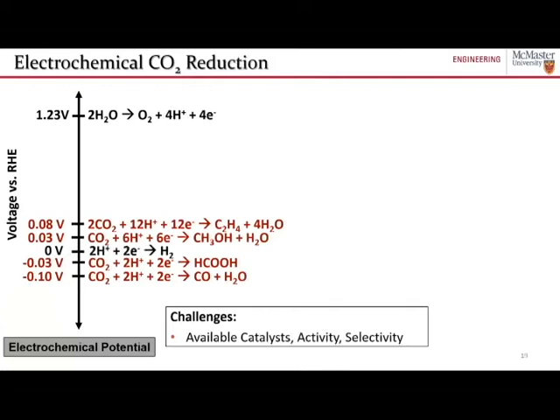Then the last thing I want to highlight is the selectivity of this reaction. I showed here a simplified picture of a CO2 reduction reaction. Overall, about 15 different products can be made from CO2 electrochemically, and every single one of them has a thermodynamic reversible potential right around the range that I'm showing here for only these 4 reactions. In addition, the hydrogen evolution reaction can occur right around the same electrochemical potentials of CO2 reduction. So ultimately, when we start running a device of this nature, thermodynamically, we can make any one of these 15 different products. So selectivity becomes a really big challenge. We want to make only 1 or maybe 2 of these products so that separations are not an issue downstream.